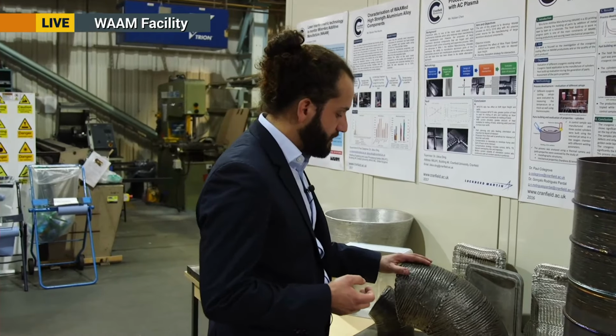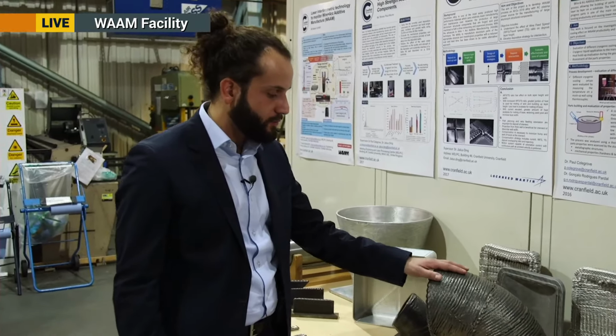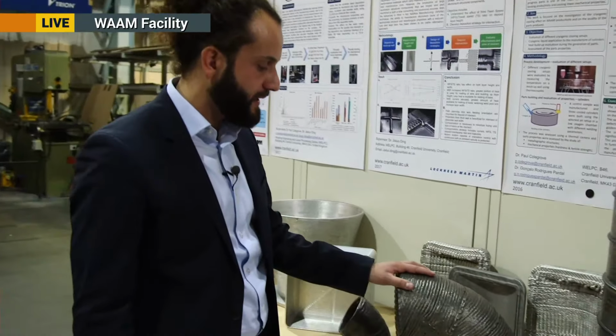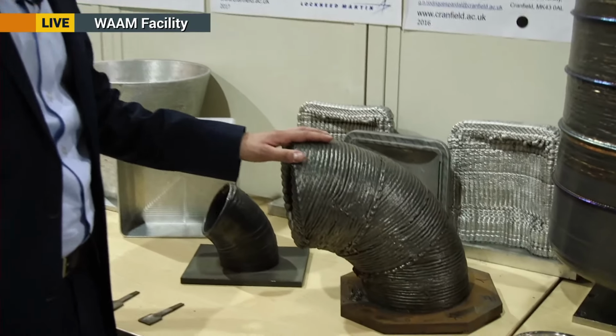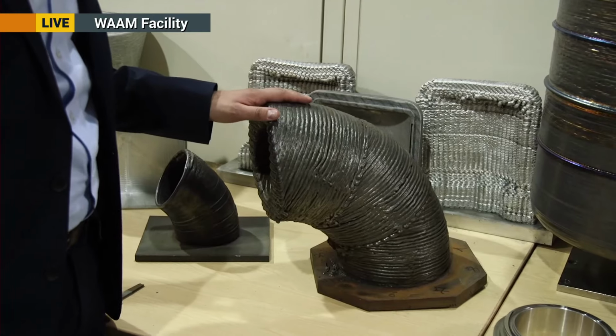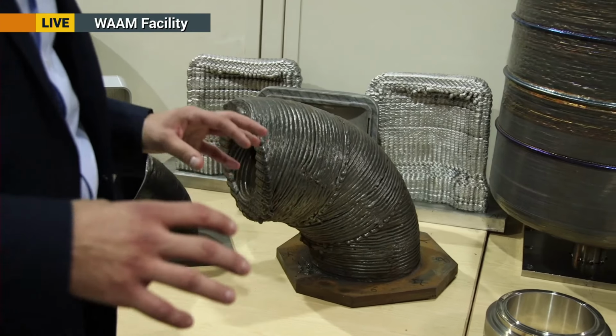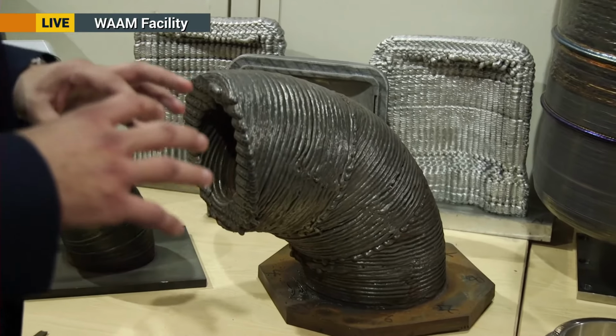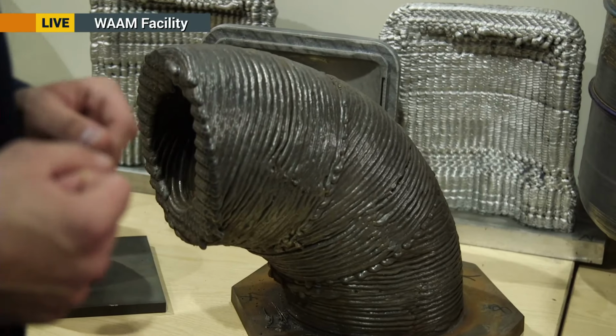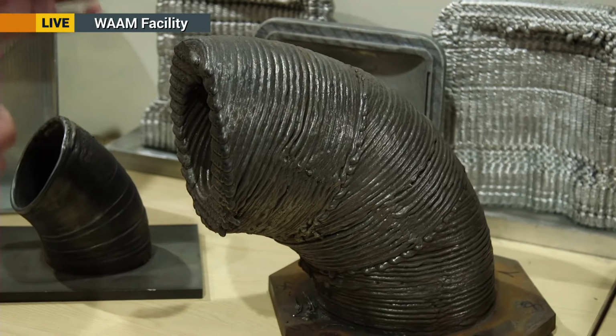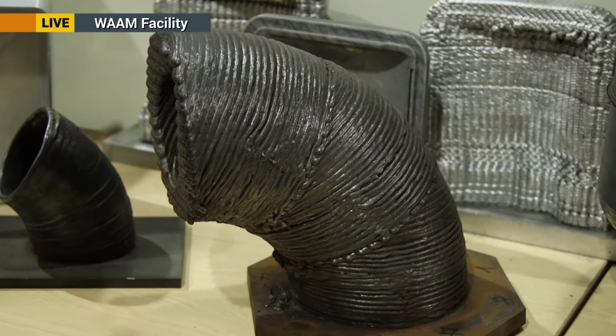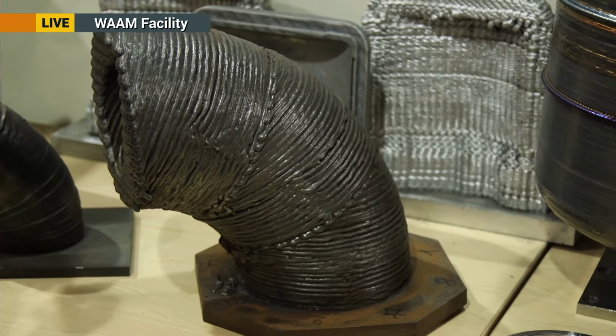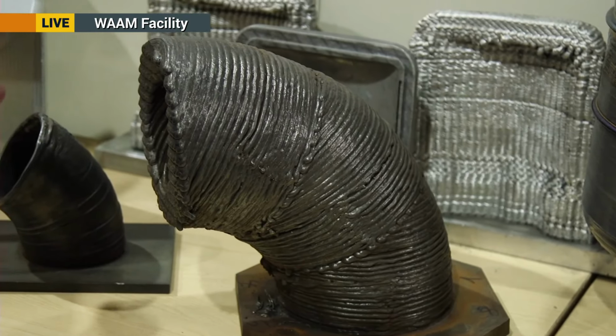As we were talking about oil and gas just now, that's one of the most challenging parts we have made. It's an elbow for a flow loop. Typically, this part would be made as a pipe, and then it would be bent once it's been taken to high temperature, and then you have to apply a protective layer to mitigate the risk of corrosion. We've done this shape in one go by additive.